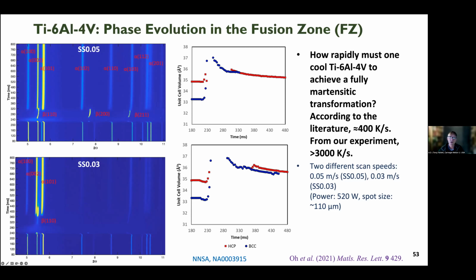And it turns out that you can detect this in the diffraction information. If you go at a high enough rate, such as you see here, you see a continuity in the unit cell volume between the beta at high temperature, that's the blue, and the hexagonal alpha, low temperature phase. Whereas if you go a bit slower, then you see jumps in unit cell size, jumps in the c over a ratio in the hexagonal phase, things like that.